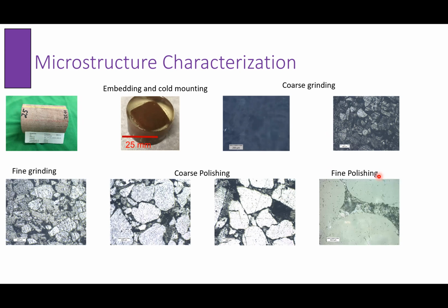So you can see that as we do our preparation procedure, we are resolving the microstructure. But we have to be very careful, because you want to just expose a fresh surface, but you don't want to damage that surface. So you want to reduce the appearance of scratches or micro cracks or even pitting. So this is what we have, the fine polishing, where everything is very well polished and we don't have scratches or pitting on the surface of it.